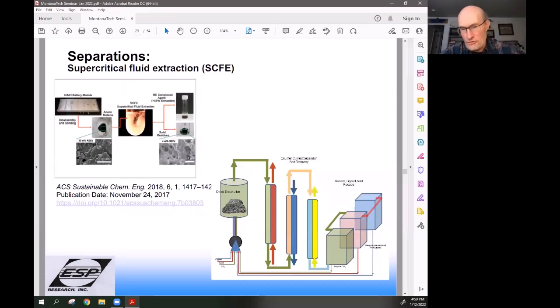Supercritical fluids have also been used, or at least thought to be used, for these systems, and they've been tested at the bench level in several cases. For example, with some nickel metal hydride batteries, after they've expired, you dissolve them and supercritical fluid extract them with extractants that we normally use in chemical extractions for solvent extraction, and you get a very similar result without the organic phase. You substitute the organic kerosene phase with supercritical fluid carbon dioxide.